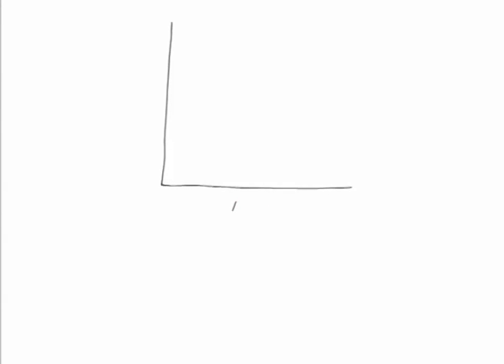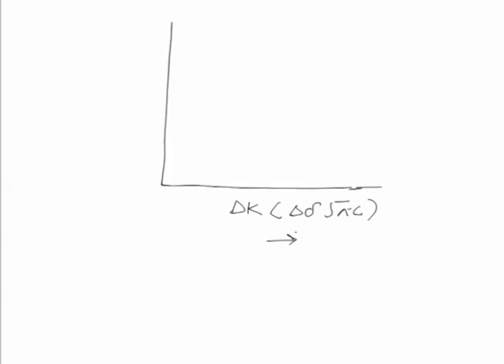To study the fatigue crack growth rate, we use delta K, the stress intensity factor range, which is delta sigma, the difference of the maximum stress and minimum stress, times root pi c. This gives us the stress intensity factor range, where c is the half crack length for internal defects and the full crack length for external discontinuities and defects. The stress intensity factor range is put on the x axis, and on the y axis we put da/dN, which indicates the crack growth rate, and we get a curve of this kind, where there is no crack growth at first, meaning the crack, even if it is there, will be non-propagating. When the stress range increases beyond a certain value, we get a curve where stable, smooth crack growth occurs.